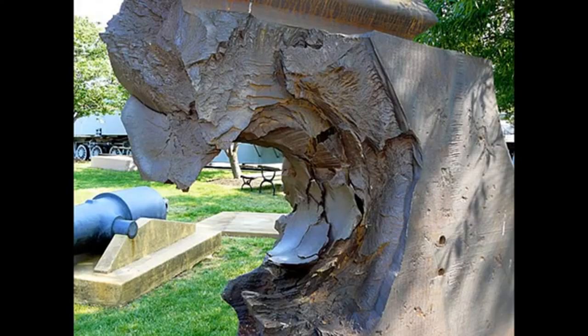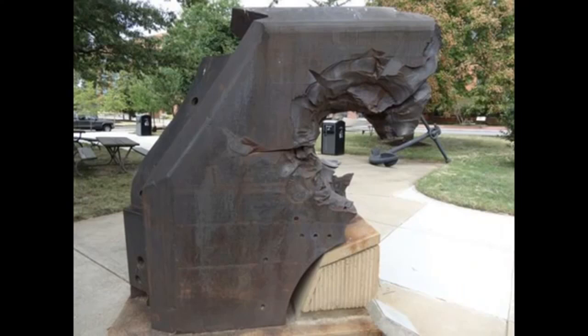Now, the Japanese modified their production process by making the hardest part of their face somewhat inside the outer layer of the armour, with a much more gradual transition between hard and soft layers. This resulted in a good quality armour at cruiser grade thicknesses, but a relatively unremarkable level of resistance per inch at higher thicknesses, somewhat compensated for by the absurd thicknesses that were manufactured for parts of the Yamato class, although this did have a few problems arising as the thickest plates that they manufactured turned out to be so massive that the cooling systems used, the various jets of water and oil, couldn't actually cool the interior of the armour fast enough, which left these very large plates vulnerable to snapping on impact even if the shell didn't actually make it through.